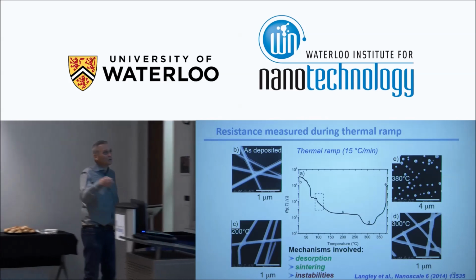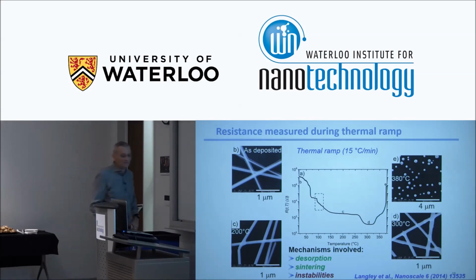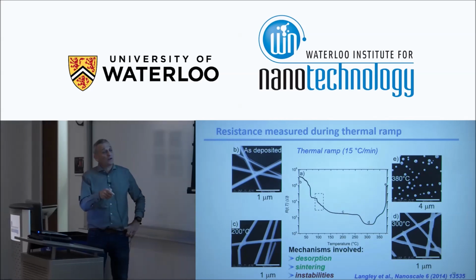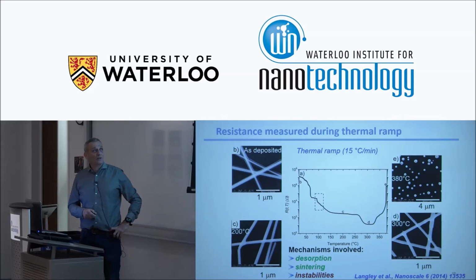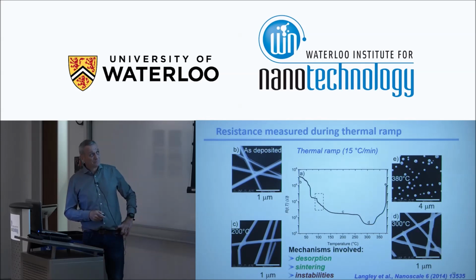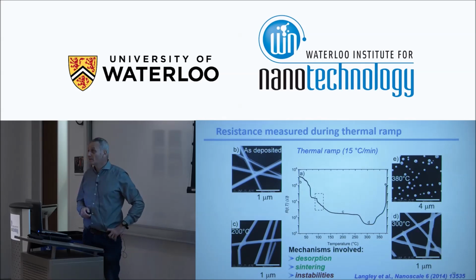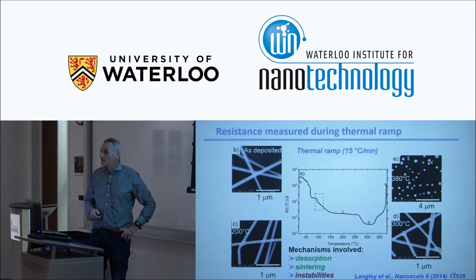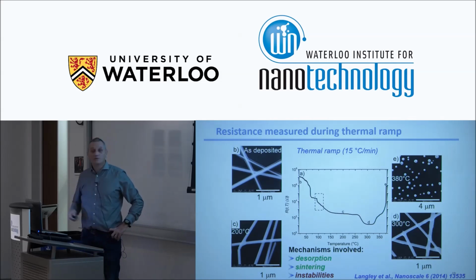And then if we perform a 10 minutes annealing at 380 degrees, then we have what we call spheroidization. This is a morphological instability, which is called Plateau-Rayleigh instability. And for sure, the network has lost its percolative nature. This is why the electrical resistance is going through the roof. Okay?